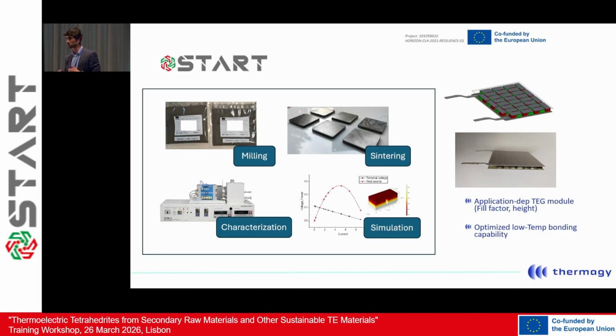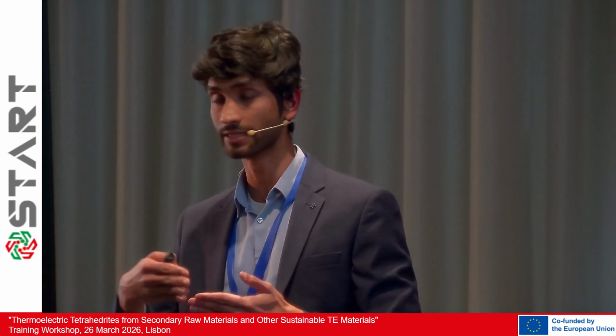So here it's around 1 to 2 microns in thickness, the interfacial layers. And that's something we are now testing, to look at what the effect is of the roughness of the material on this interfacial layer